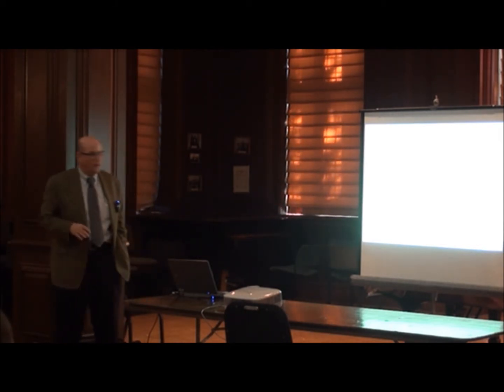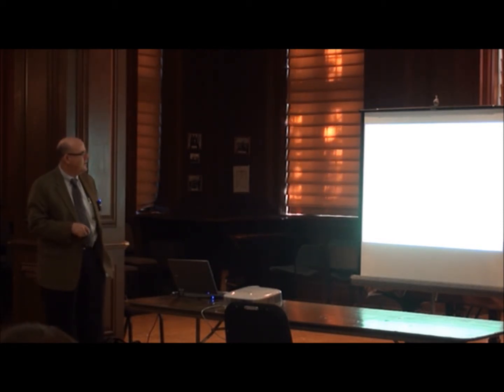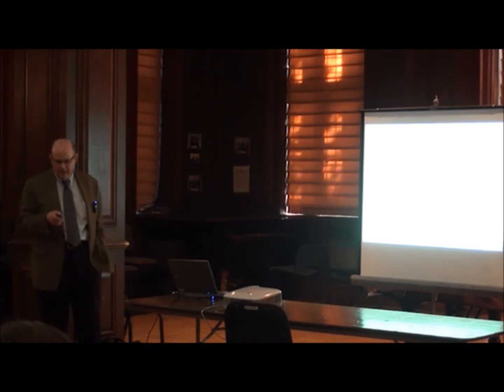When things are just plastically deforming, for a given load, the real area of contact is fixed. It doesn't depend on surface roughness or anything like that. On the other hand, as you get to a certain regime of roughness, and that's critical how I said that, not just amplitude, not just spacing, but the proper combination, then all of a sudden the real area of contact starts to grow pretty quickly as the plasticity index gets smaller.